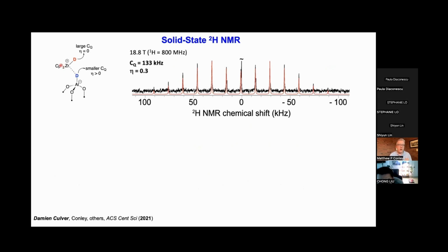So then we go into this with a model. This is what we should have. We should have a CQ that's small with an eta greater than 0 for this bridging deuteride, and then a terminal deuteride with a large CQ, eta of 0. We run the experiment. We had to go to Santa Barbara to do this at higher field. We end up seeing only one peak, and we kind of beat our heads on this for a while, thinking about, why is it one peak? And it's the same thing that happens in solution NMR happens in solid state NMR. If you're just seeing one peak, cool it down.